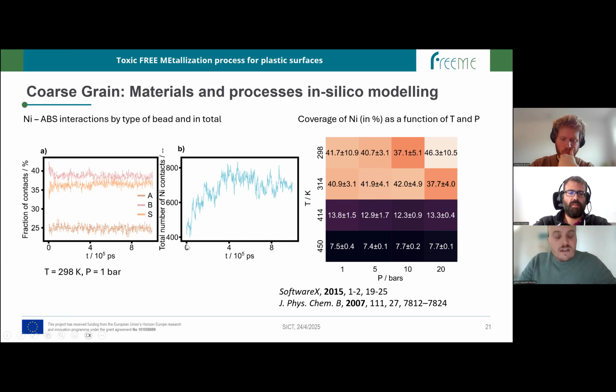pressure. Then what we can also do is count the total number of nickel contacts with the A, B, and S beads in order to get some kind of estimation of the coverage of nickel on the surface of the ABS chunk that we have built, as a function of temperature and pressure.